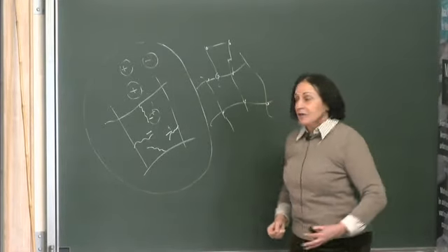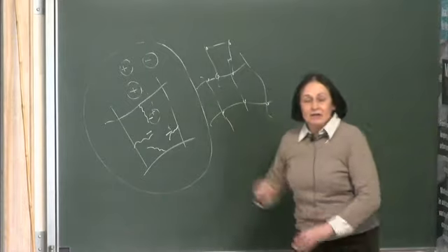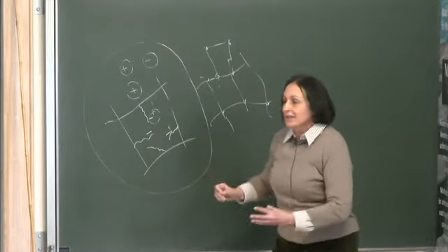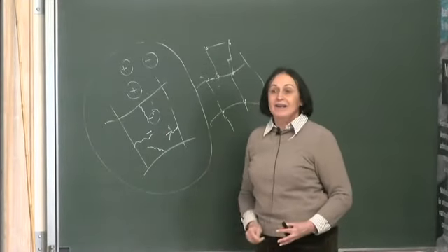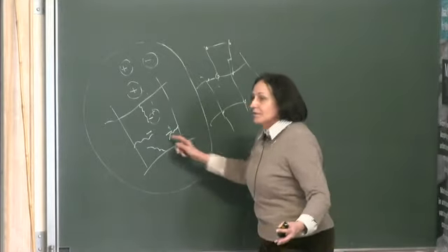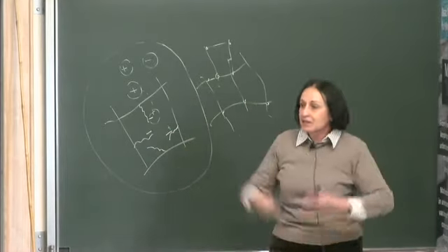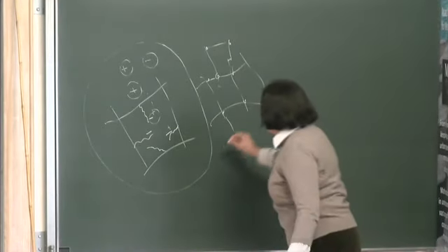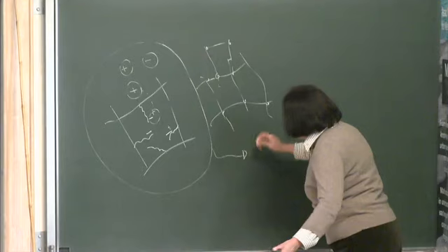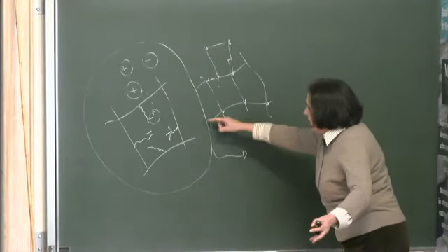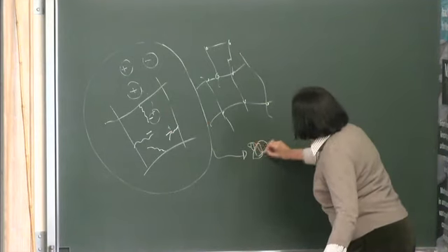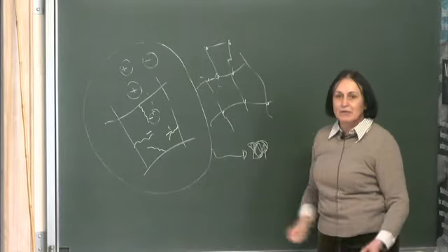each other. On the other hand, as the positive ions keep coming in and reattaching, at some point there is not so much repulsion force, so there is no reason for the system to pay so much elastic energy, so it contracts. And as I'll show you, we'll talk about this later a little bit more precisely, you can see that there is a state where now this network, these pieces of the network, are all bundling up on themselves.